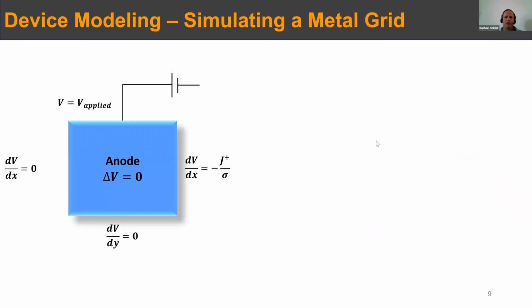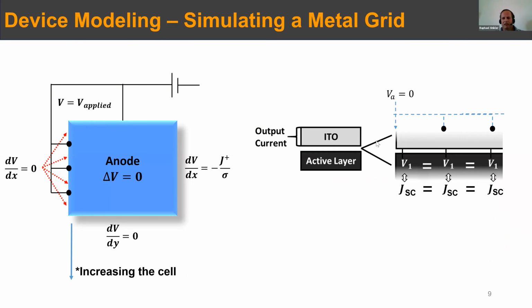And what we then did is we wanted to add a metal grid in order to improve the conductivity and the collection. Now, when you add the metal grid, one thing you should ask yourself is where you would like to put these metal grids? And in our model, we can just introduce these points as collection points where they have a voltage equal to 0, and therefore they are situated at the short circuit currents.